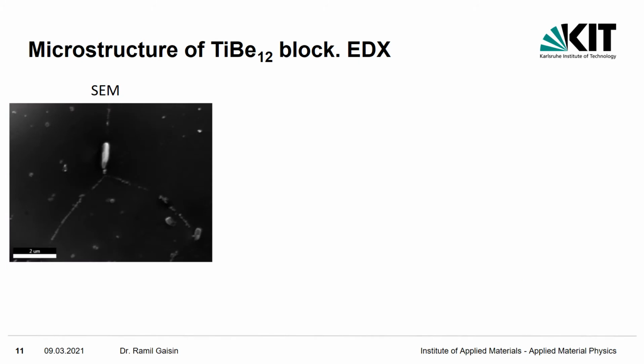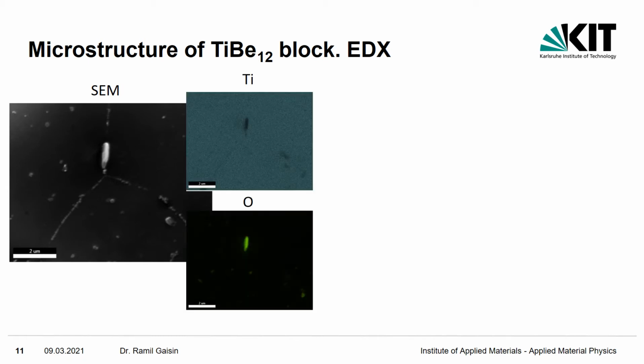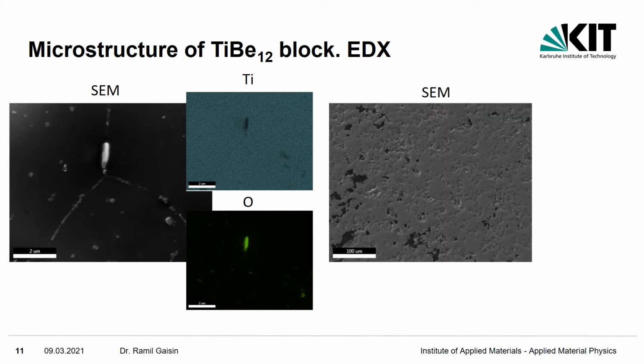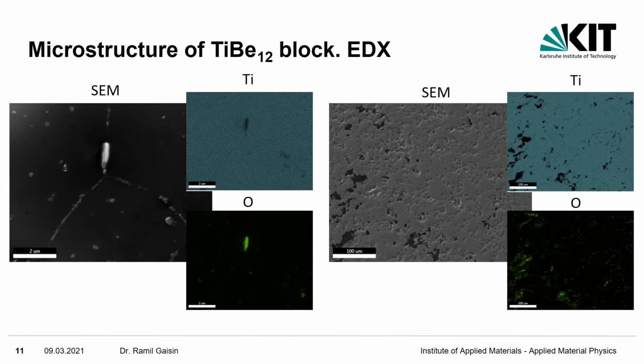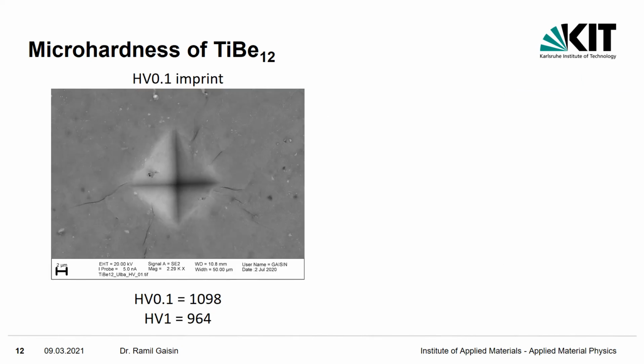Let's analyze what other phases are in the microstructure. Here you can see a triple junction with some small particles around. Some of them contain oxygen and do not contain titanium, which means that they are particles of beryllium oxide. At lower magnifications, larger dark areas can be detected, which are composed of beryllium, and this means that there was an excess of beryllium before beryllide synthesis.